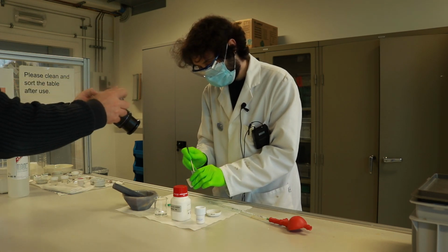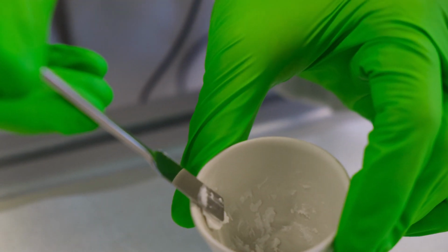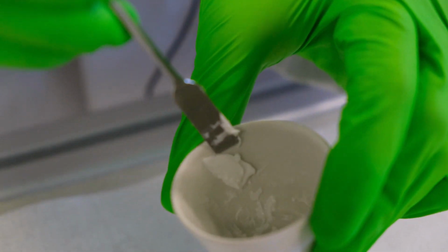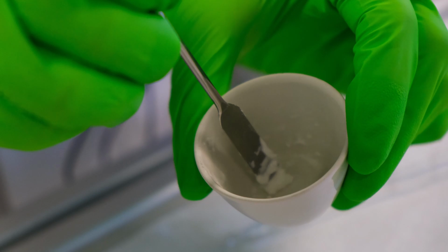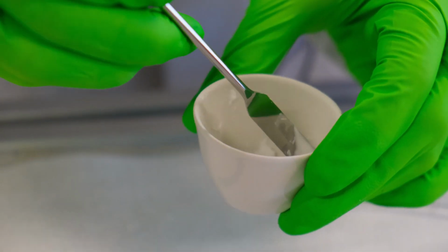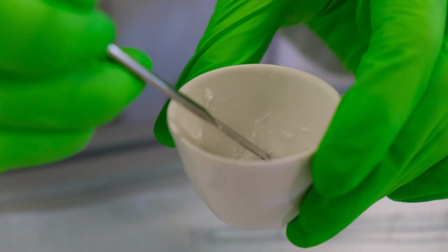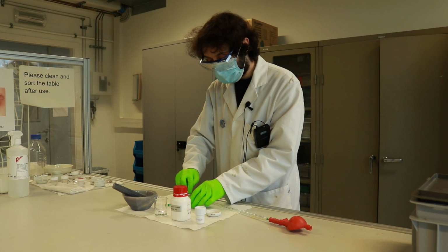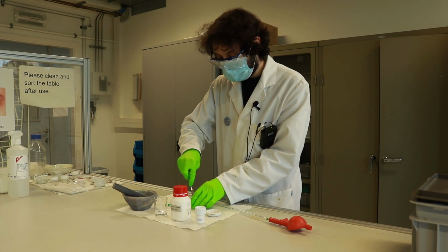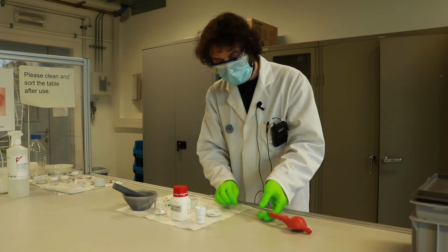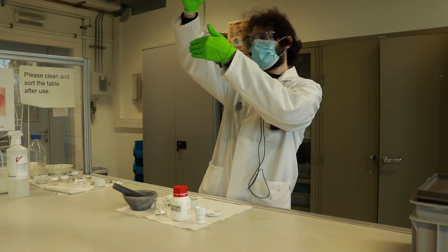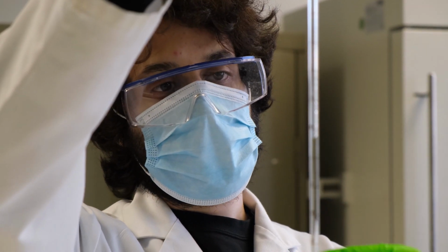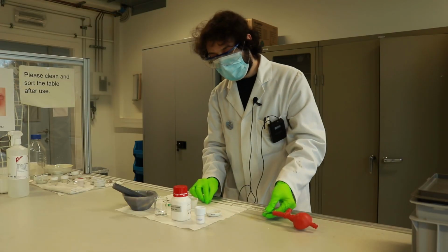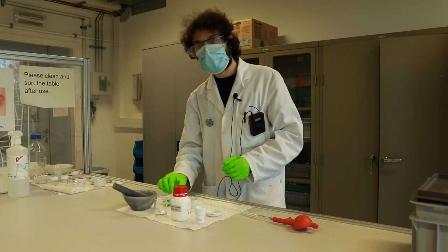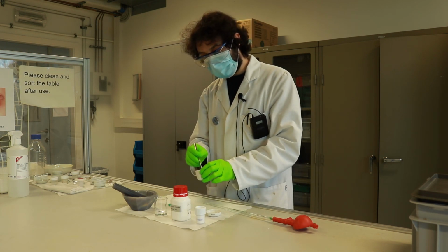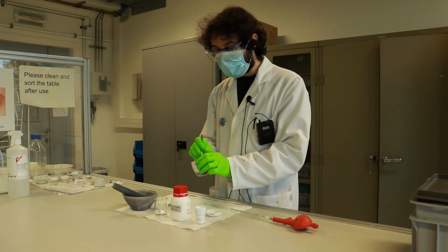After mixing, you can already see that my fine powder is completely wet. However, there is no excess liquid around it. Having measured both the amount of water I've added into this crucible and the amount of starting support, I can easily calculate the pore volume. Let me check. So I've used half a gram of gamma alumina, and I've needed around 0.65 milliliters, which means the pore volume of this support I'm working with is 1.3 milliliters per gram.